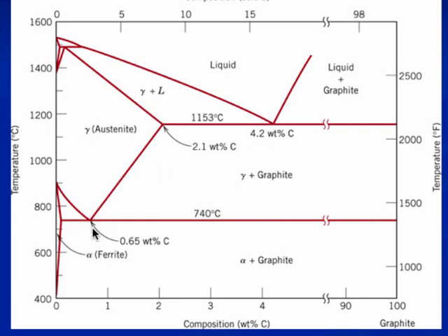The other V here is also a eutectoid reaction, but it's all solid. It's austenite converting to ferrite and graphite, or more commonly ferrite and cementite — one phase going to two. That's a eutectoid. It's all entirely solid. And this is at the heart of the heat treating of steel. We're going to spend quite a bit of time on that in the next lecture.